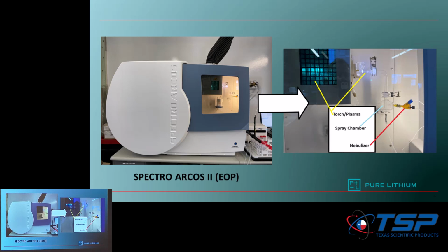So the ICP we use is a Spectro Arcos, and it uses a Rowland circle, and that's the main reason that the resolution at 670 for the lithium is so high. It separates it, so lithium 6 will actually fall slightly off from lithium 7, and if you run the two next to each other, you will physically see two peaks.